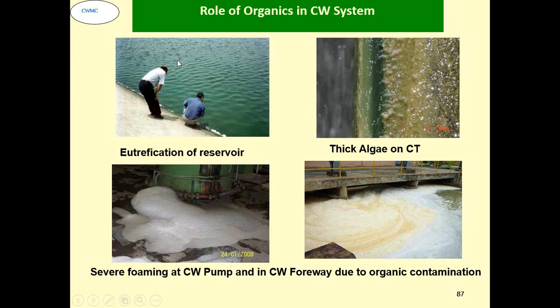Now what you see here in the left side picture is the make-up water reservoir of a cooling water system. The water that was coming here had a high level of impurities, especially microbiological or organic loading. Because of this, a powdery green algae was formed on top of the reservoir and below. This algae was aerobic in nature, so it took away all the dissolved oxygen from the top of the water, and below that anaerobic bacteria like SRB etc. started growing and then started fouling the system and causing microbiologically induced corrosion problems.